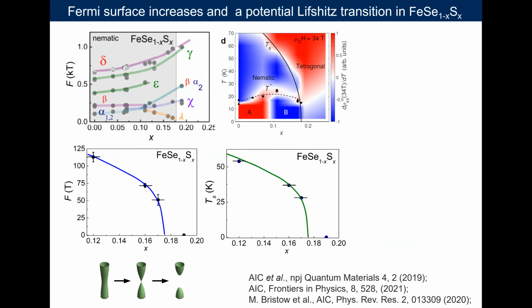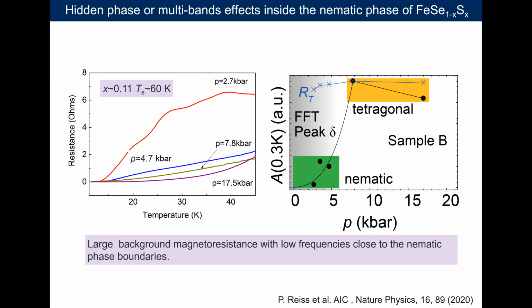And here the color represents the changes in the slope inside the nematic phase, and we call it nematic A and nematic B, just to emphasize that there are differences in the magnetotransport behavior already inside the nematic phase. So there are two signatures in the B phase, let's call it. A dominant low frequency appears, and the resistivity at low temperature shoots up, as if the system becomes more localized or orderly magnetic, we don't know exactly why. And this low frequency, which appears, seems to disappear together with the nematic phase. So it's clearly linked to what happens there.